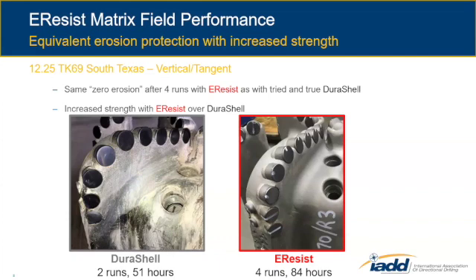We have a question: what's the main differentiator in your materials to go from abrasion resistance to erosion resistance? A lot of it is particle size — some of it's a blend of different particle sizes, and whether you use different shapes of carbides. For the matrix specifically, it's generally going to be particle size and a blend of different particle sizes.